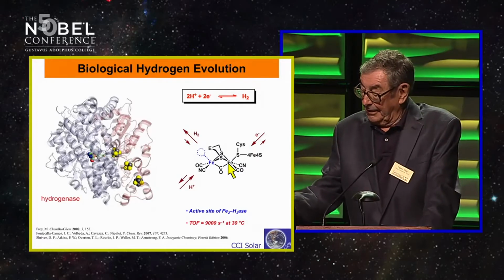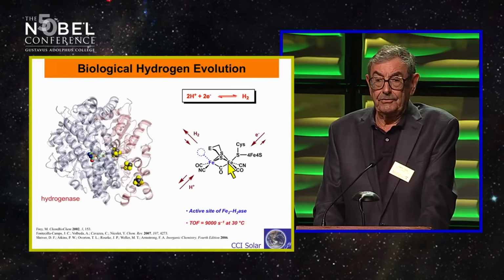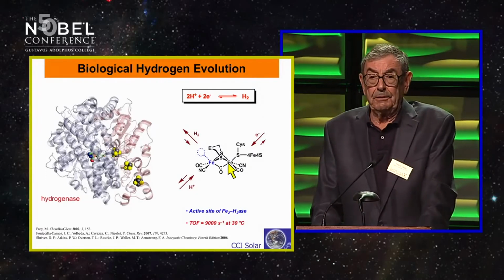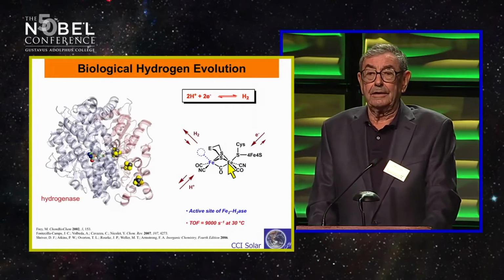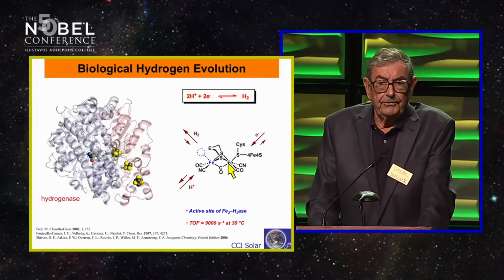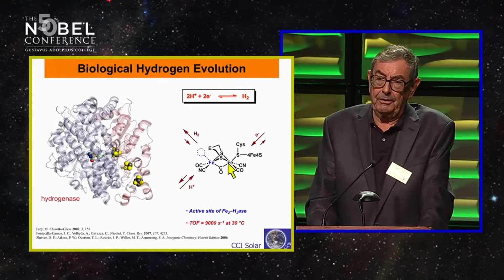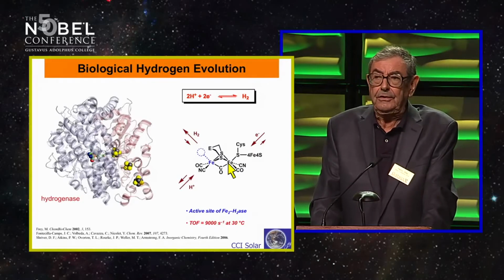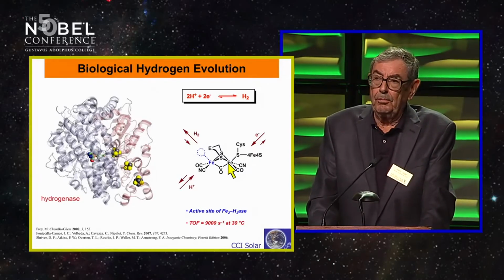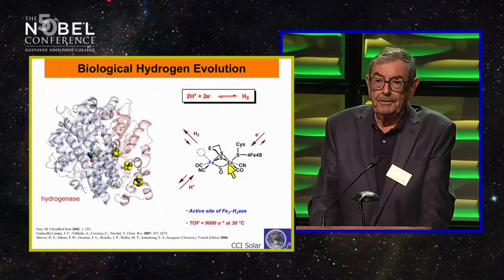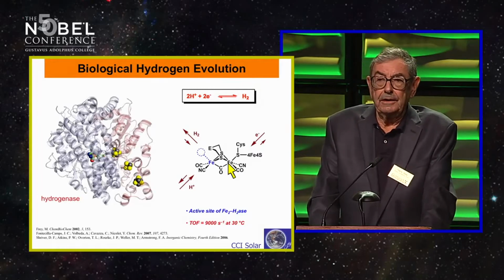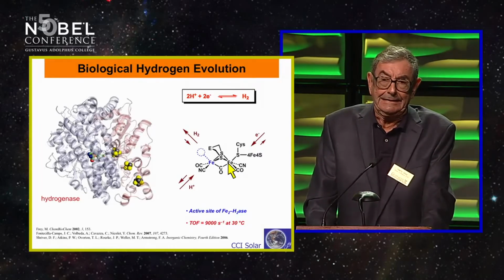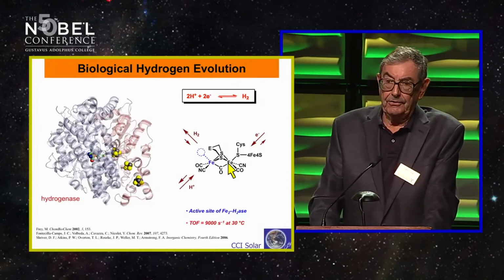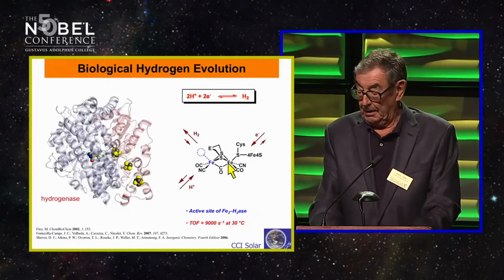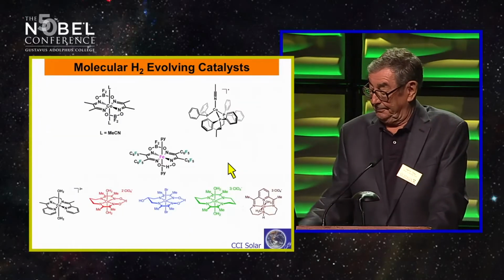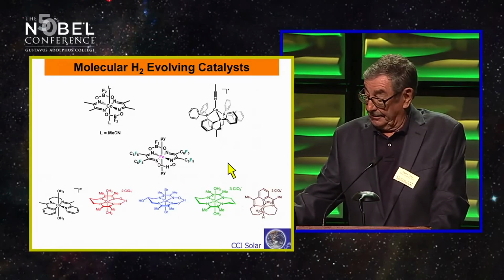So lots of people are working on this problem now. Bioinorganic chemists all over the world are trying to synthesize these biomimetic centers that will work, but we're not quite there yet. So what we did was start a worldwide effort of synthesis of new catalysts from inorganic compounds, cobalt, nickel, and iron mainly, some molybdenum. With this worldwide effort, we've now ended up with about 40 working homogeneous catalysts for hydrogen evolution that work really quite well. And the Caltech Hall of Fame is here. These are the ones that were developed and studied at Caltech.